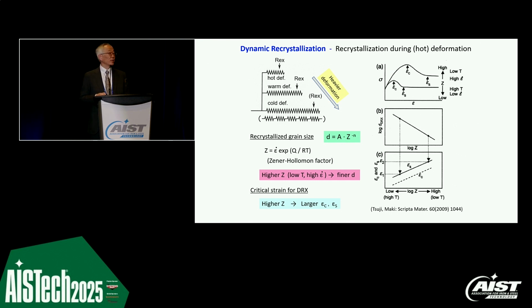So dynamic recrystallization, of course, is a very nice phenomena because grain size can be obtained, defined by processing condition, strain rate, epsilon dot, and temperature, in terms of the Zener-Hollomon parameter. However, when we take a look at the flow stress at the higher temperature or lower strain rate, we have relatively low flow stress. The recrystallization initiating strain is small, and also the finishing strain is small. However, if we go to the larger Zener-Hollomon parameter value, Z value, we can have such critical strain increase to the higher strain level.